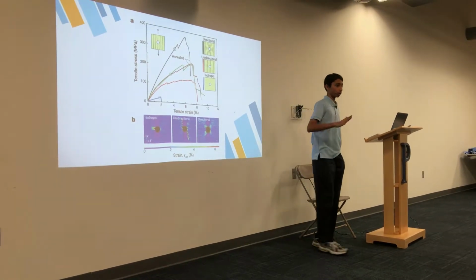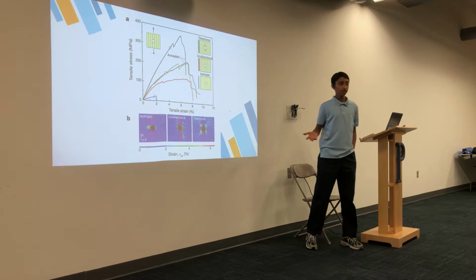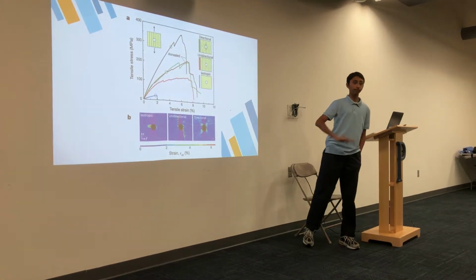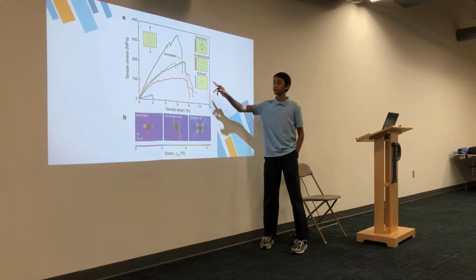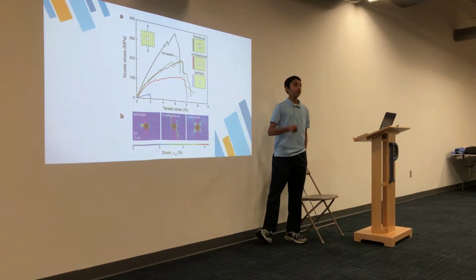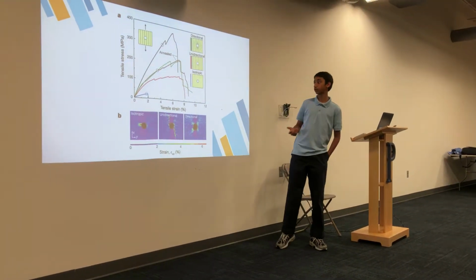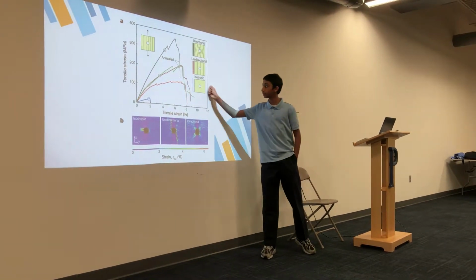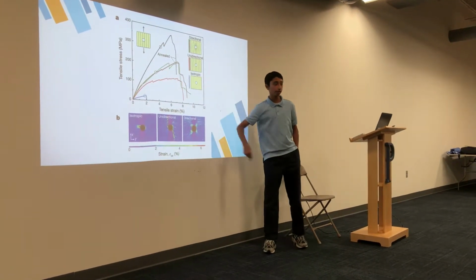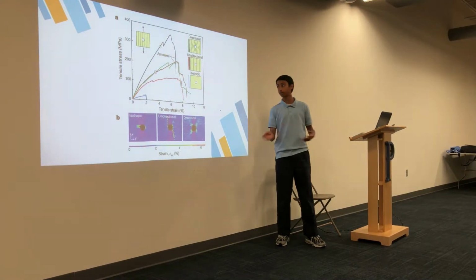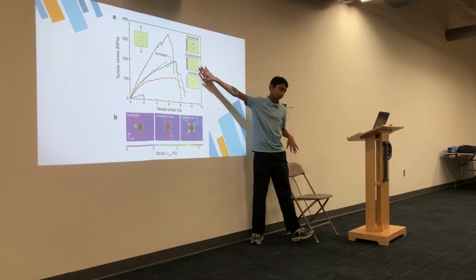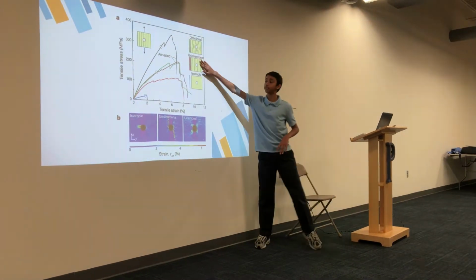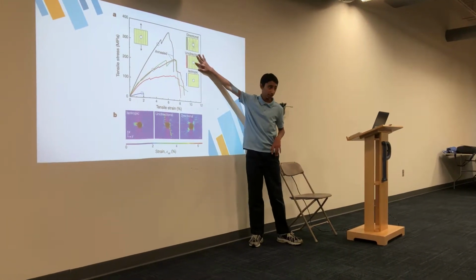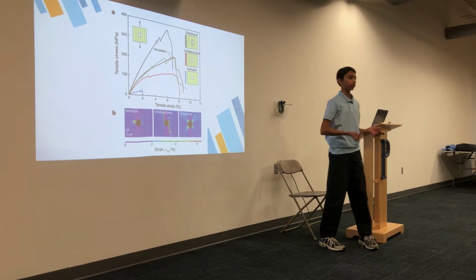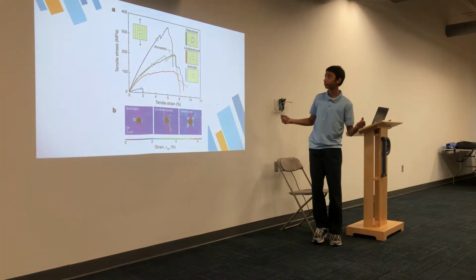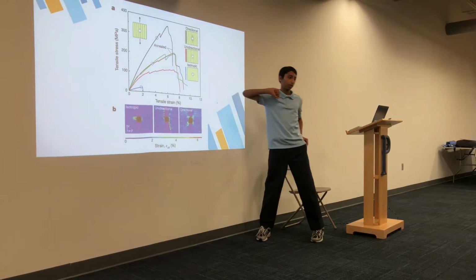And that's what we call isotropic, where you don't really have a grain. It's very smooth and flat and consistent all the way through. And isotropic materials have the same properties no matter what orientation the molecules are in. So if I took a knife and I cut this isotropic material horizontally and vertically, it'll cut the same way. It's not going to be more difficult one way or the other. Unidirectional, you can see here that it does have a grain. It has these vertical lines, but this hole in the middle, which they're using as a kind of hook when they try to rip the material apart, they don't really adapt to the hole.